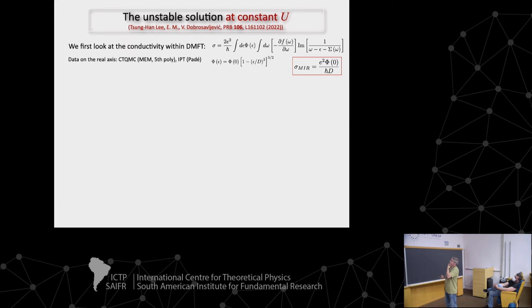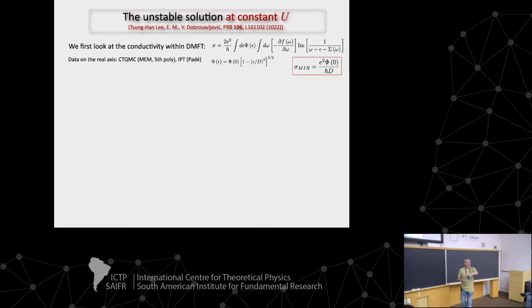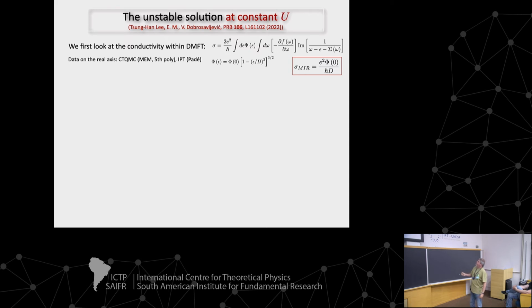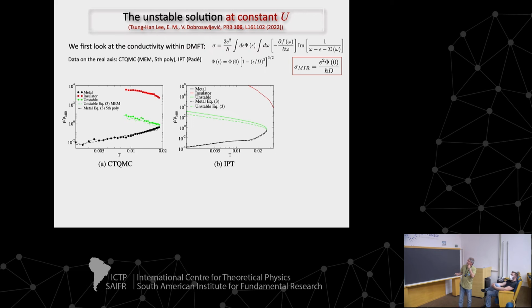So the first thing we did was the following. You can use dynamical mean field theory to calculate the conductivity of the metal, the insulator, or the unstable solution, the domain wall center. These are the formulas. I'm not going to explain that. This is standard in dynamical mean field theory. So what you see here is the following. For the metal, here's the resistivity, it goes down. For the insulator, it goes up. And for the domain wall center, it's sort of in the middle, but it goes up. These are different methods for solving the impurity problem.